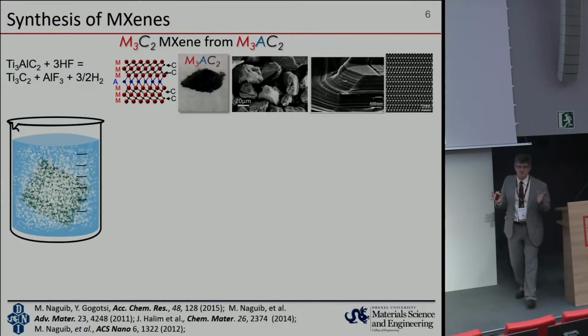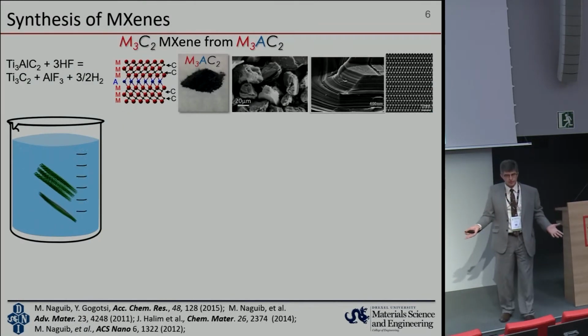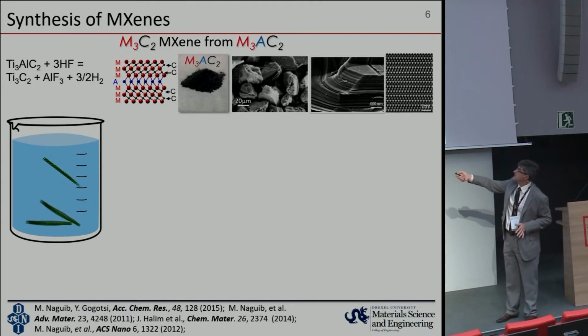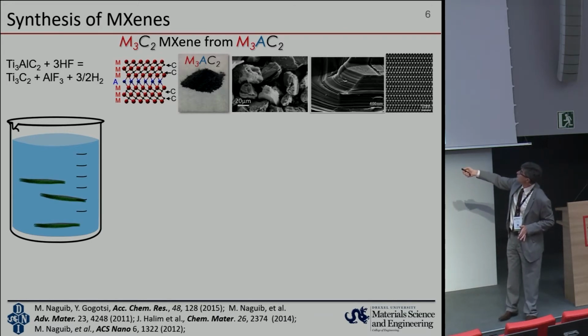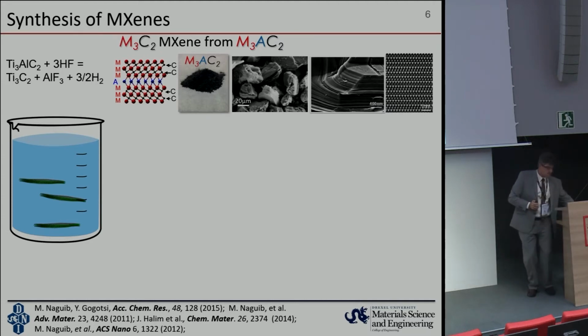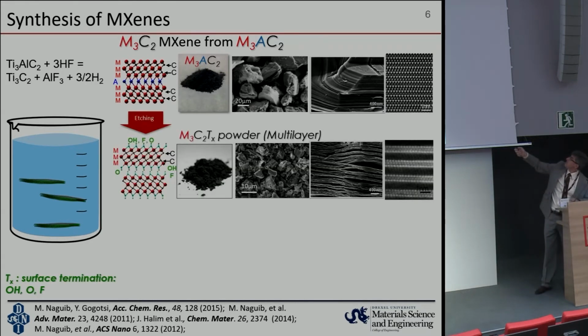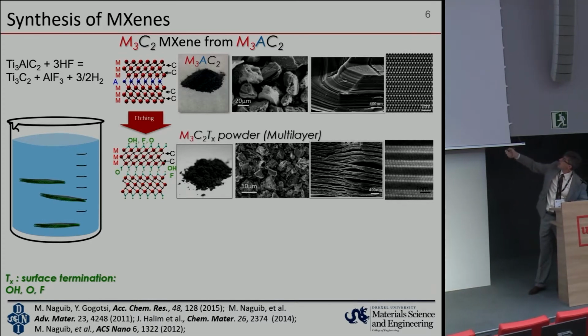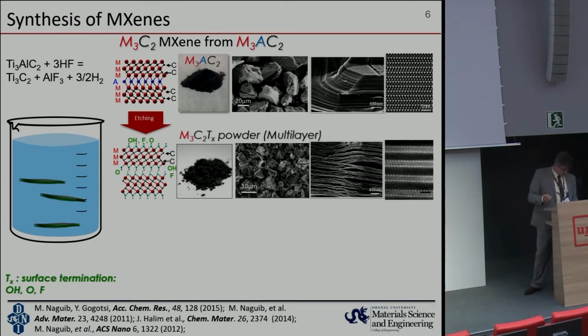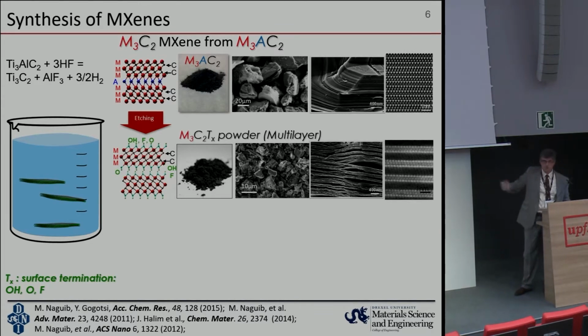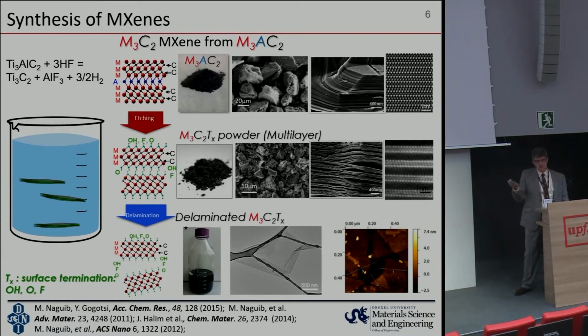And the synthesis process is actually very simple. We take ceramic powder, we dump it into a solution. Initially, we used HF, even though we now rarely use this etchant. And what we do, we dissolve this layer of aluminum. As a result, if you look at high-resolution STEM images, the layer of aluminum is gone. What is left, in this case, is Mo2TiC2. So there are only carbide layers left. They're not bonded anymore, or there is a weak hydrogen bonding because they get terminated in solution by oxygen, OH groups.